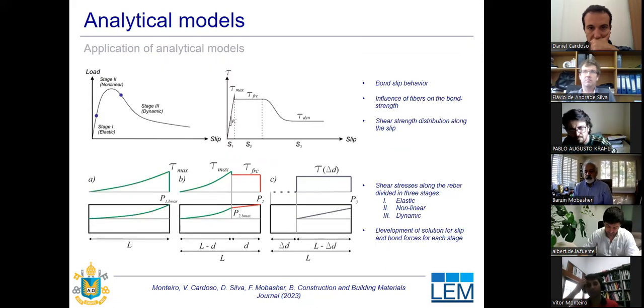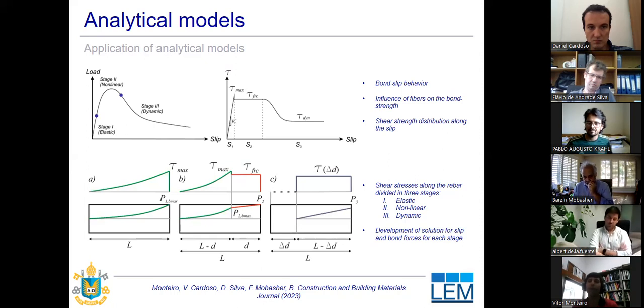Before presenting the results, I would like to give an overview of the analytical models that were applied for the quasi-static tests. The analytical models try to evaluate the bond slip behavior through three distinct stages. The first stage is the elastic stage, where there is a perfect bond between the rebar and the concrete. Then there is the non-linear stage, where there is an unbonding length going on until the complete bond length is unbonded from the concrete. And then stage three is characterized by the dynamic motion of the rebar. That means a rigid body motion of the rebar coming out of the concrete matrix. So in order to make this model work, we need to define the shear stresses along the bond length.